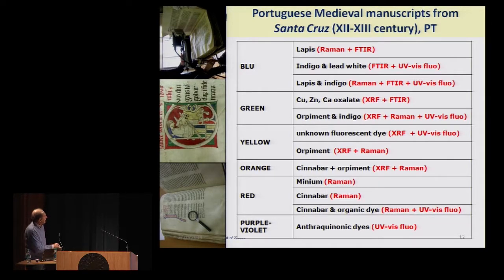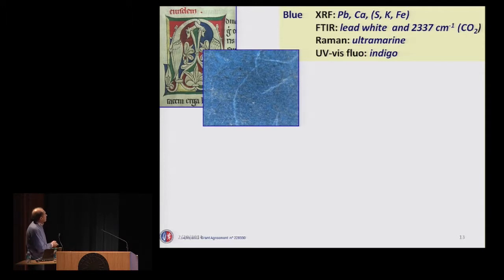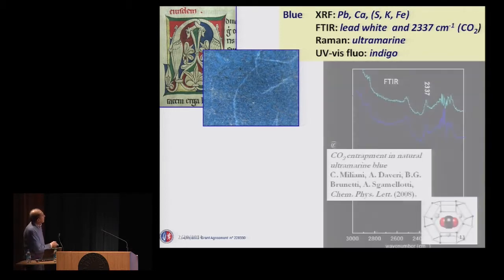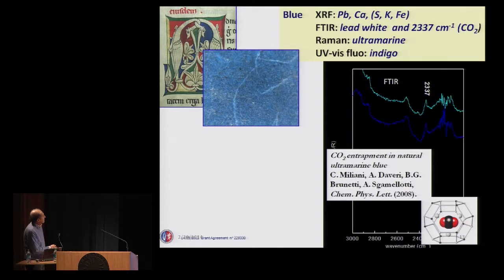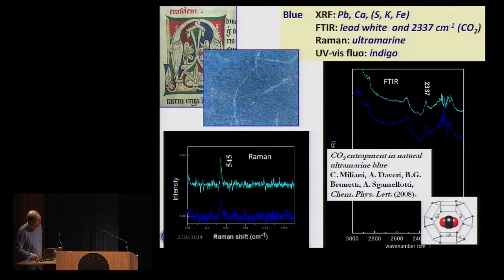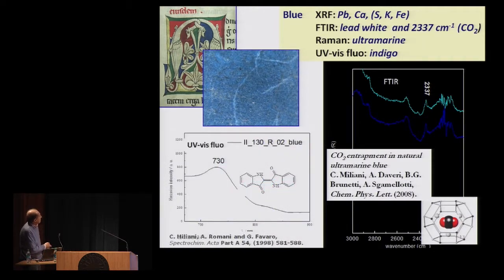You can see lapis and indigo were characterized by Raman, FTIR, and other techniques. For example, this blue was characterized by XRF to be due to lead, calcium, and a minor component. The lead was due to lead white, as identified by infrared spectroscopy, but ultramarine blue was also detected through the presence of this band that is typical of the CO2 that is trapped inside the beta cage of the mineral lazurite. Ultramarine blue was confirmed by Raman, and the presence of some indigo was also found in this area through the fluorescence observed with a maximum at 730 nanometers.